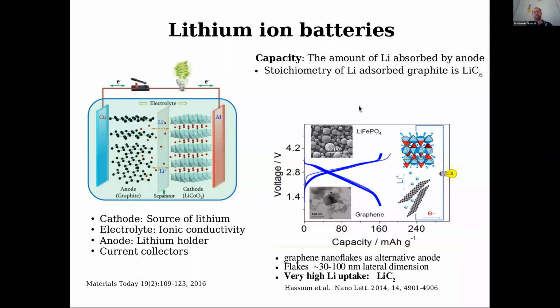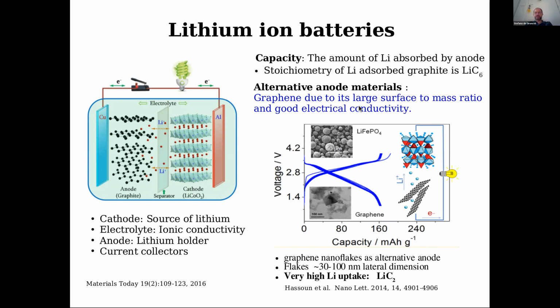So that would be a factor of 3 in the capacity, the amount of energy that the battery could store. And so it's interesting to study the interaction of lithium and graphite. We did some work. Again, this is relevant for what Emine will talk about later, because between lithium and graphite there is a relevant charge transfer. And so she will talk about how to deal with long-range interaction.